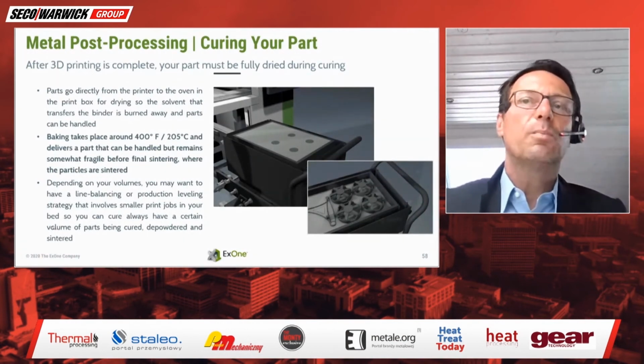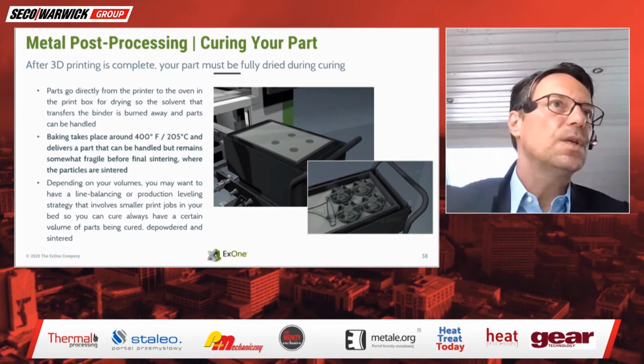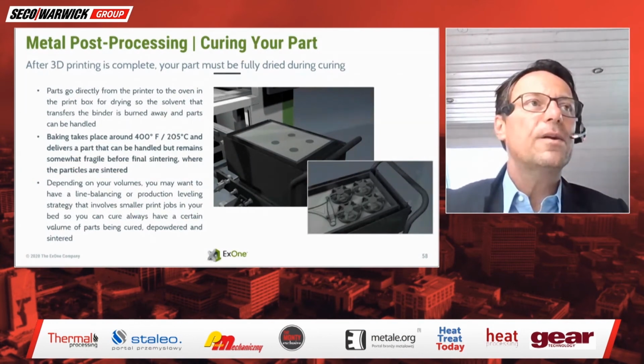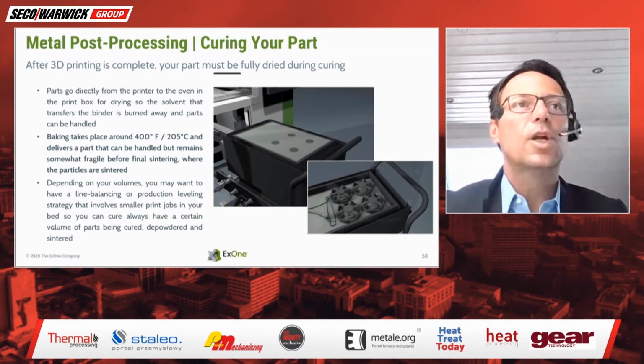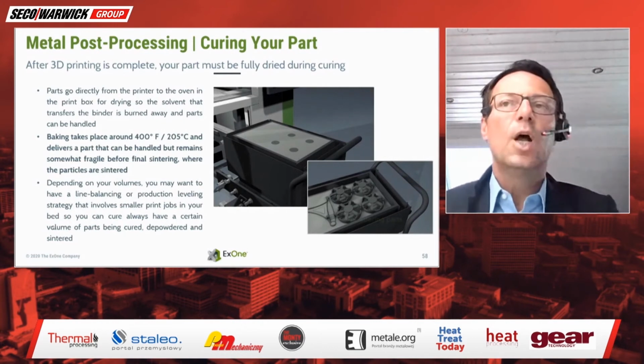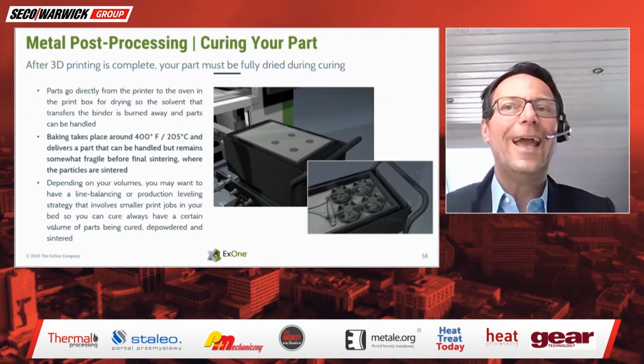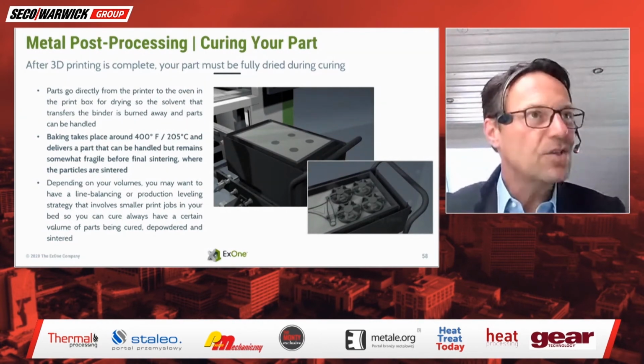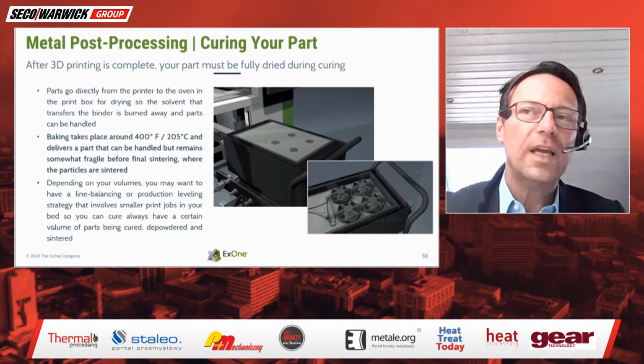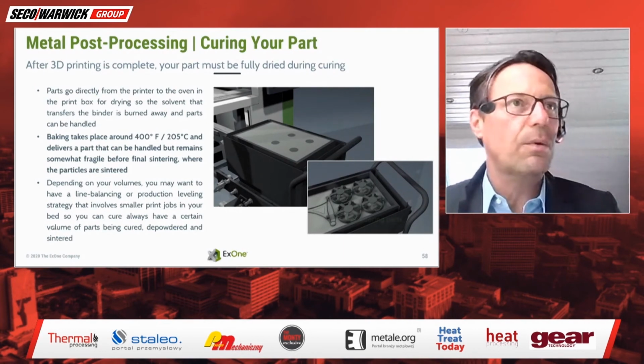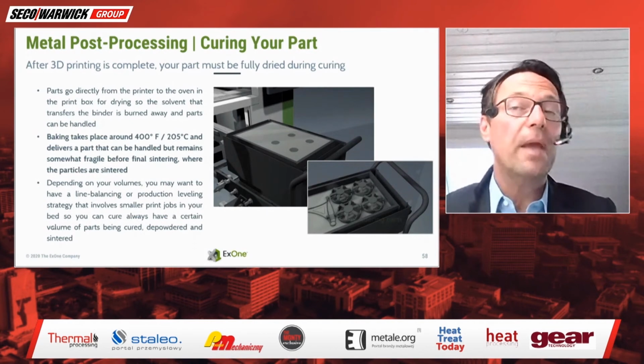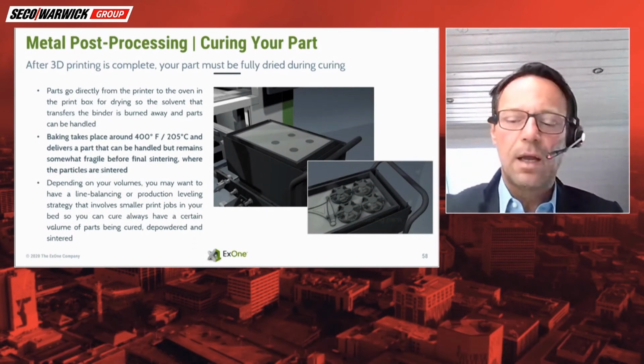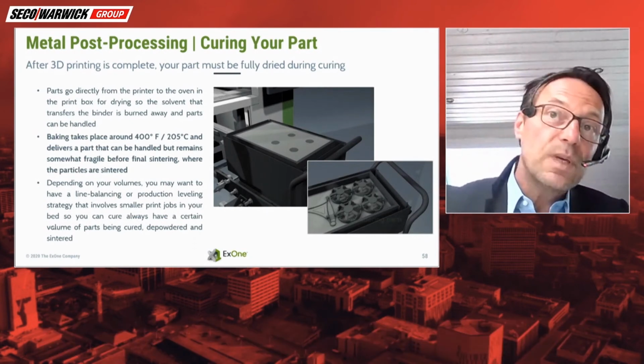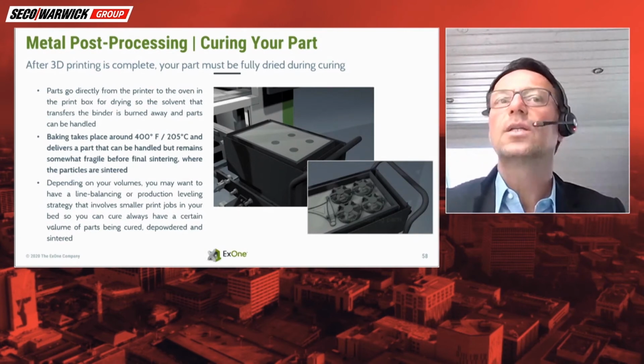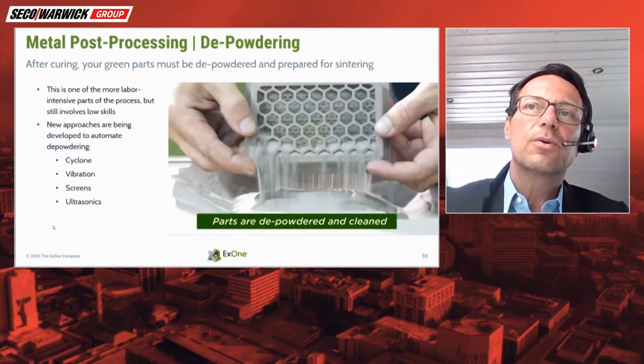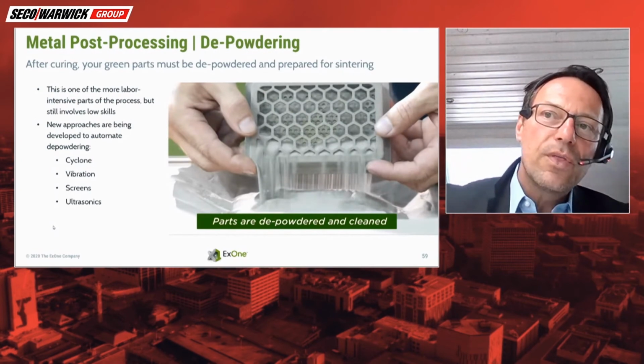Curing your part is necessary to cure the binder, so curing the glue between the particles, to make a solid part which you can handle. It's still not as solid as you think, because it's in that green state. That means it has a tensile strength of something like 6 to 8 megapascals, so it's kind of fragile. And as we don't want a fragile part, after the depowdering process, we go for the sinter process.